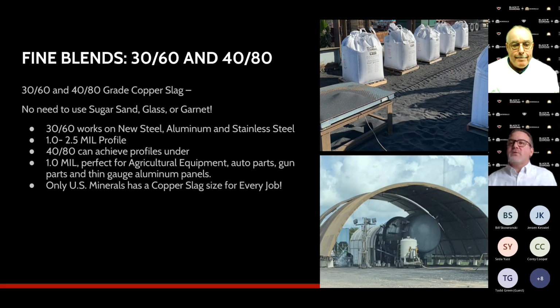And then our fine blends, the 3060 and 4080, you don't need to use sand, glass, or garnet. The 3060 and the 4080 work wonderfully on new steel, aluminum, stainless. It gives you 1 to 2.5 mil profile, and especially the 4080 can get you a profile underneath that 1.0, kind of use it as a sweep blast for stainless and aluminum.